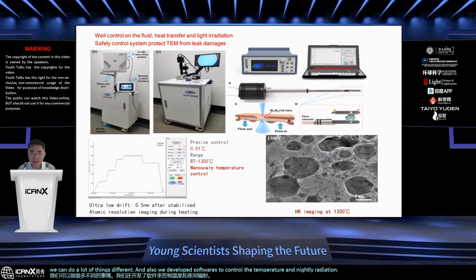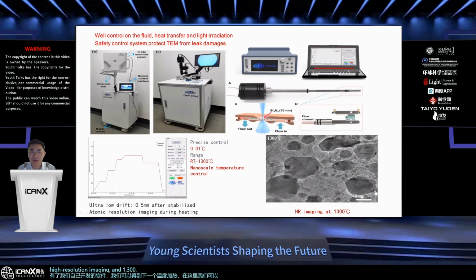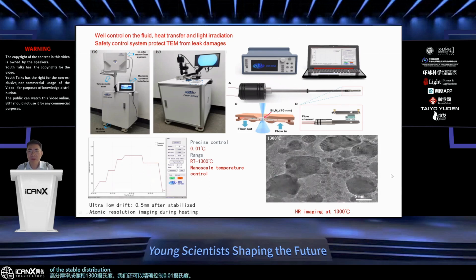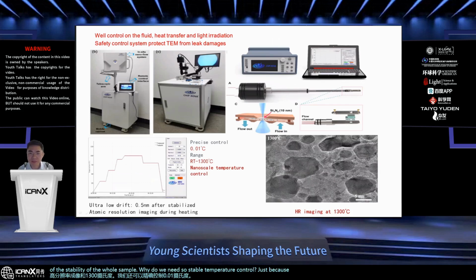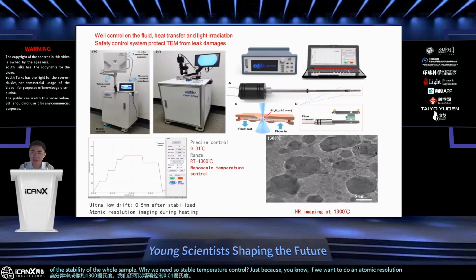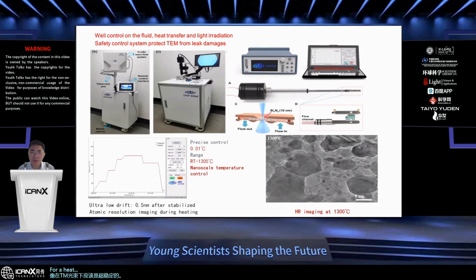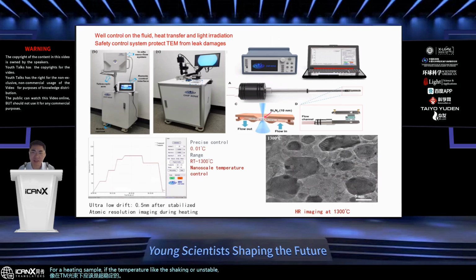So with our self-developed software, we can get the temperature heating, and here we can get high resolution imaging at 1300 degrees C, and also we have precise control of 0.01 degrees C of stability of the whole sample. Why do we need such stable temperature control? Just because if we want to do atomic resolution imaging, everything under the TEM beam should be ultra stable.